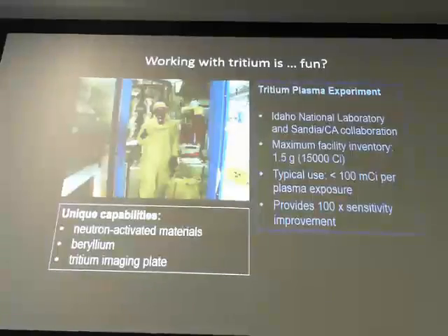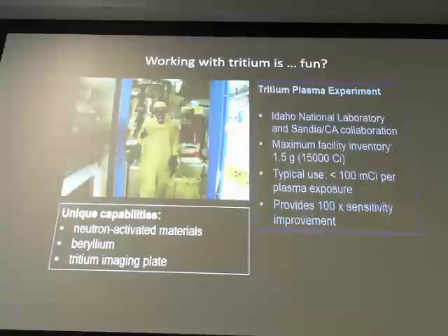In terms of flux, an ampere per square centimeter, that's 10 to the 19 deuterium or tritium per centimeter squared. In terms of fluence, if we really pushed it, we could probably get to the mid 10 to the 22 per centimeter squared range, and for ITER, you'd probably be about 2 orders of magnitude higher than that. So there's a way off from what we can do here, but this is not the highest flux.